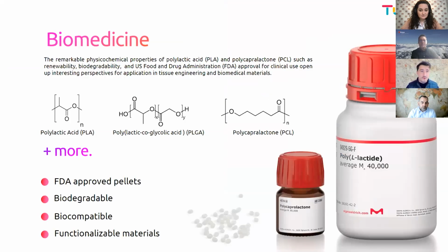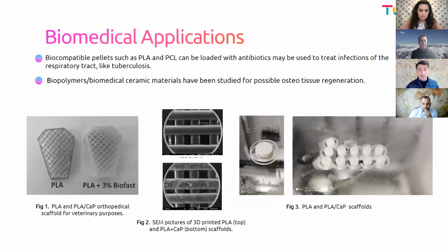As previously mentioned, for the biomedical sector, chemical grade FDA-approved polymers such as polycaprolactone or polylactic acid are required. So this can be used to fabricate scaffolds using different blends that contain active biomolecules such as antibiotics in order to treat different pathologies or infections. And here we can see some biomedical applications, just to give you another example. Blends containing PLA and an inorganic material. In this slide, we can see that they are using calcium phosphate, which has been widely studied for bone regeneration.